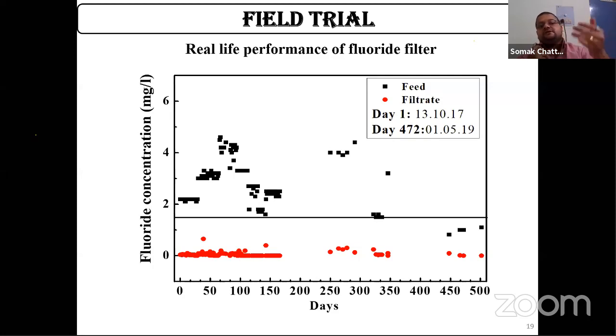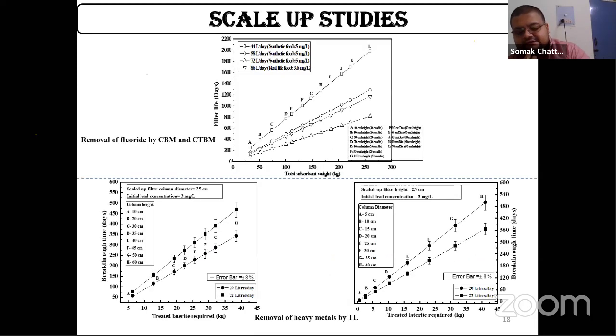Now in case of this fluoride filter, it was a situation where we were running the solution with gravity, that is from top to bottom. So once we use that, it will not use the full bed, and therefore it is one of the best possible cases, and hence your filter will run for more days. So we found by experimentation that the data we got over here usually varies around 20 to 30% from the normal values that we get from the scale-up studies.